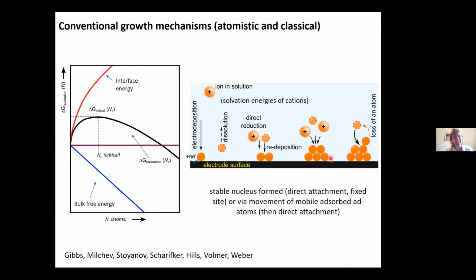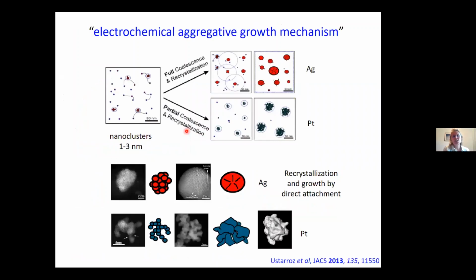And terms such as instantaneous and progressive were coined to perhaps describe different regimes of metal nucleation deposition. Although those terms now are being used with caution. So I would say that a lot of the theories for longer term nucleation probably fit pretty well. The challenge becomes when you start to look at the shorter terms and whether some of these pictures truly describe everything that's happened. And so this is where, probably about 10 years ago, Jon Ustarroz in Belgium started some really nice work, starting to look at early stages of electrodeposition to try and understand the mechanism of growth.